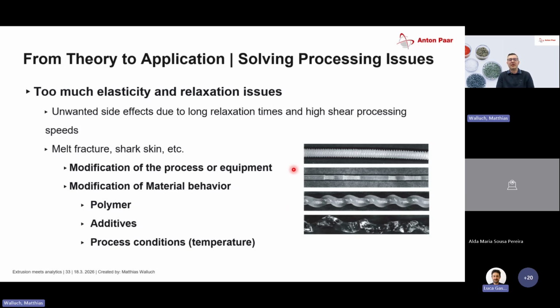We could increase the temperature, we could slow down the process, we could add additives, we could change the polymer. And to know what to do and what the reason is, rheology is the right tool to find out what makes the process better, because usually you don't want to go down with the speed, because speed is time and time is money.